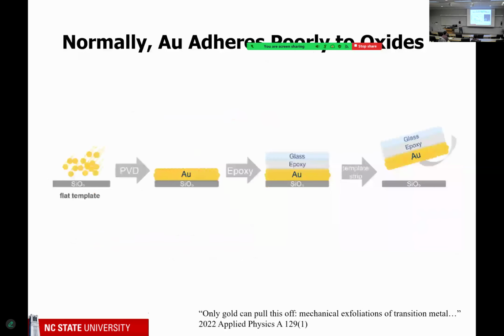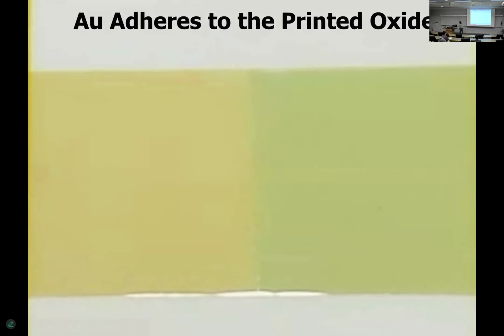So it's a very stable conductor. And then, like I said, the surprising thing is gold. If you take gold and you deposit it on almost any surface, but especially oxides like, say, glass. So here's our gold film on glass. This is a thicker layer, so it's actually a film. If you just come with some glue, like epoxy, you can actually just rip that right off. I mean, ripping's even being generous. You can just easily peel it off.